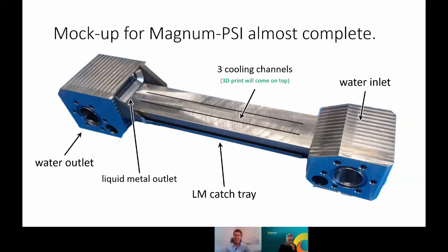I should say I can add to that, the European DEMO team, which is trying to design a more conservative design that will definitely work, is very against the use of lithium, for very good reasons. Not only do you have only a tiny bit of breeding, because of course it's still a very thin layer with almost no neutron absorption or stopping power, you will have a lot of tritium absorption simply from the plasma, because lithium and hydrogen isotopes really like each other. So you can absorb the entire fuel, your tritium reserve, in no time. And we know how much effort it takes to breed that. So that's not something you want to do.